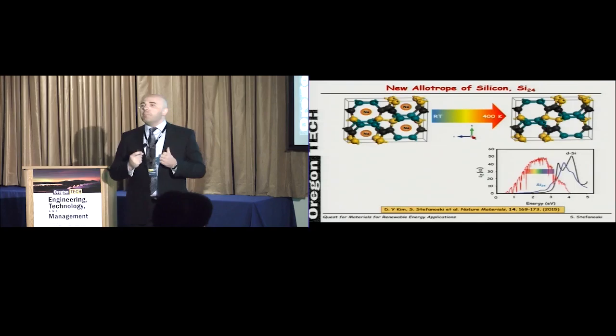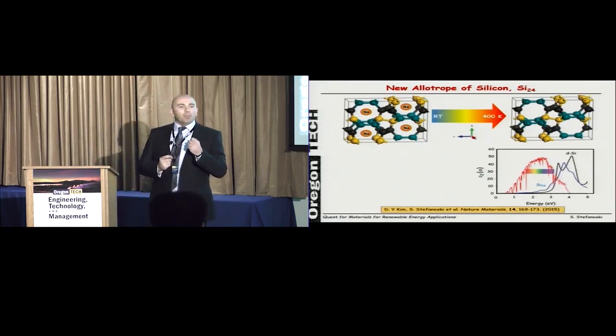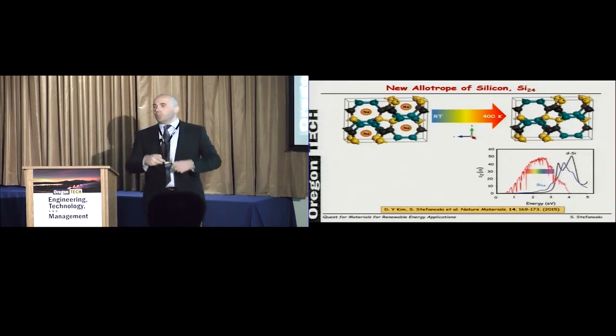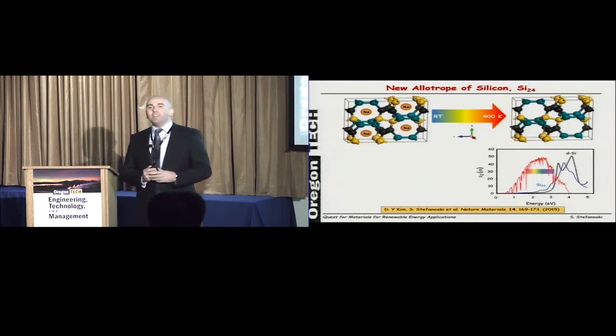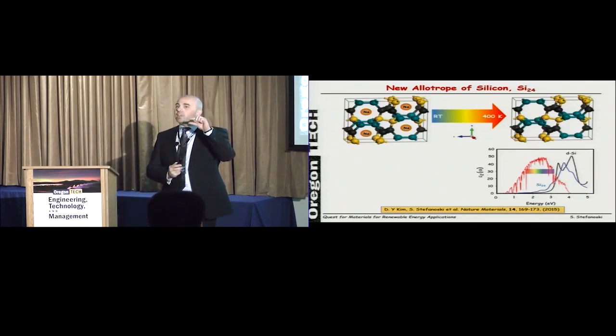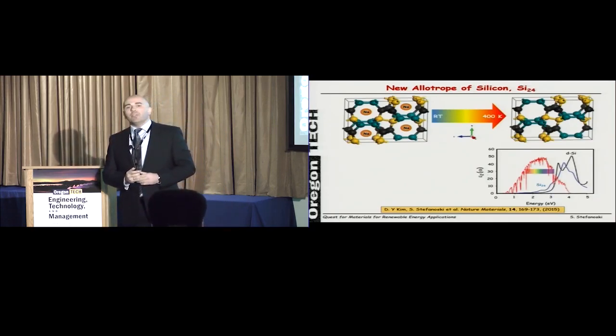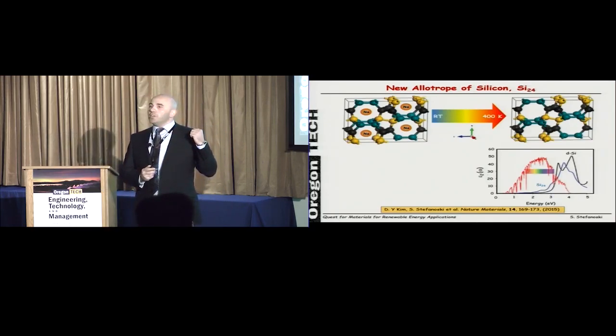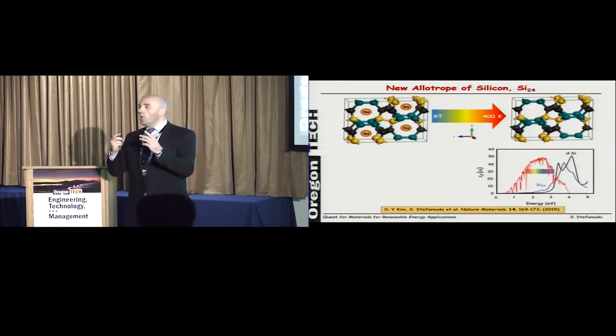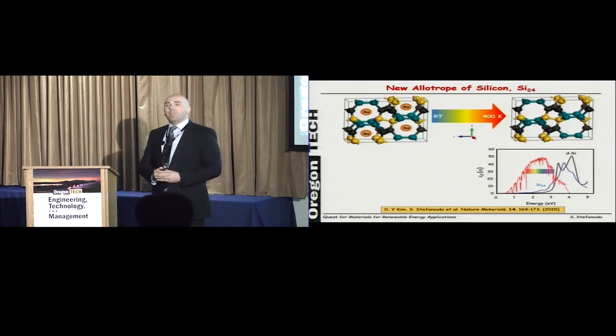What does that mean? Silicon, for example, regular or conventional silicon, is an indirect bandgap semiconductor, which means that wafers have to be relatively thick in order to achieve relatively good conversion. This material has direct and indirect bandgaps that are almost the same. That's why we call it an almost direct bandgap semiconductor. Therefore, we can go with relatively low thicknesses with this material.